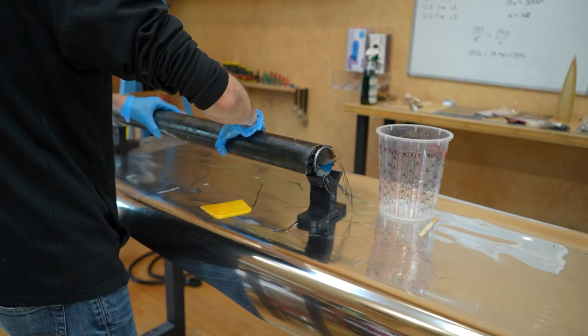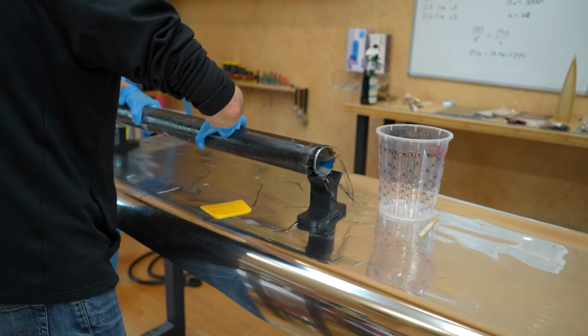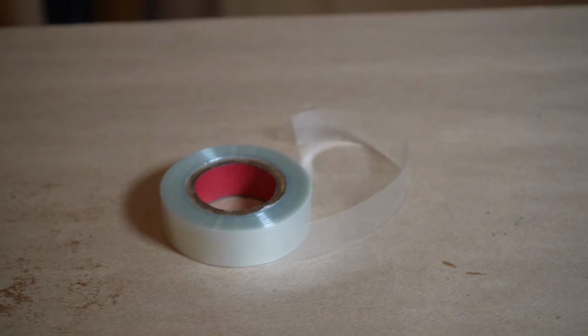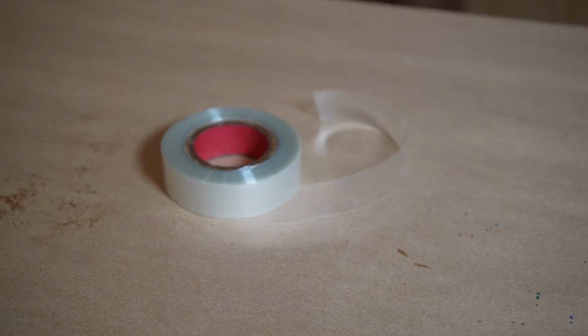Once the 2-ounce fiberglass is smoothed down, I wrap the entire tube in a layer of high-temperature heat shrink tape. This heat shrink tape will provide compression and squeeze out the extra epoxy I don't want in the tube, while leaving a smooth surface finish on top.